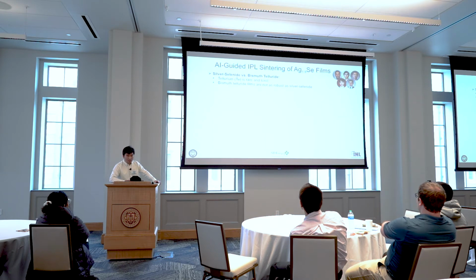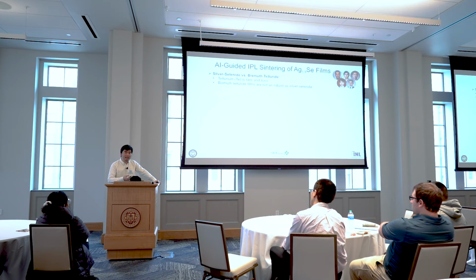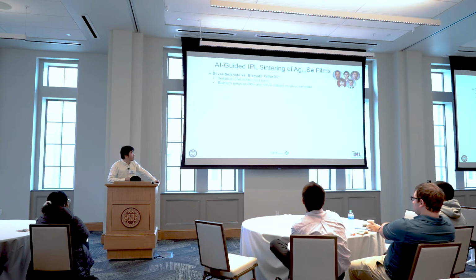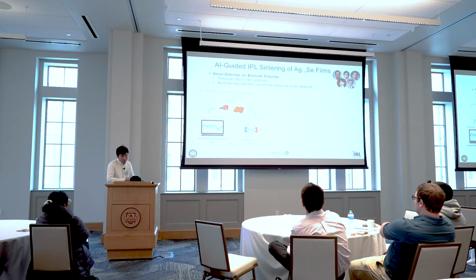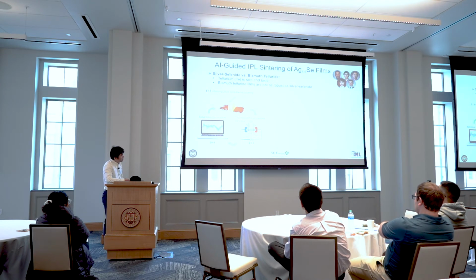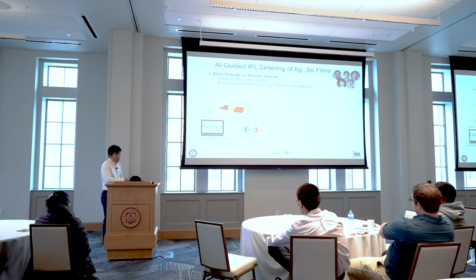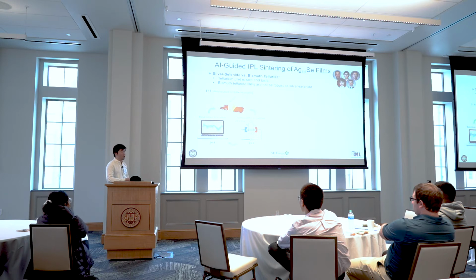So to optimize this process, we used it to sinter the so-called silver selenide film, and this film has an efficiency that is not as high as the state-of-the-art bismuth telluride, but it has certain advantages, such as being non-toxic and more mechanically robust. So this is the procedure we do the iteration. Okay. So this is an iteration among the thin film fabrication, and then the sintering, and also property measurements. Okay, in order to measure the thermoelectric property here specifically, we're measuring the power factor. And then we feed the data into the AI algorithm and use Bayesian optimization to guide us what we should do next in order to improve the thermoelectric property. Okay? And this is an iterative process until we can no longer see much better results. Okay?